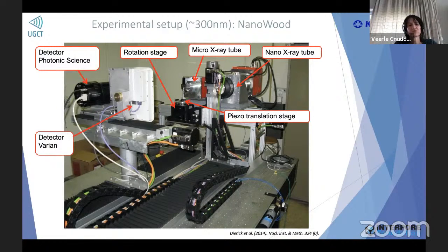Varian is more sensitive for higher energies, while Photonic Science is ideally for lighter materials, lower energies. So depending on what kind of sample we have, we switch the X-ray source and the X-ray detector. There are also translation stages, and this allows us to play with the distance between, for instance, source to detector or source to object.